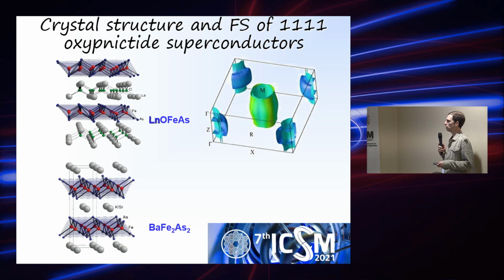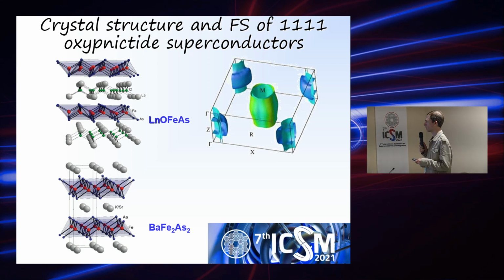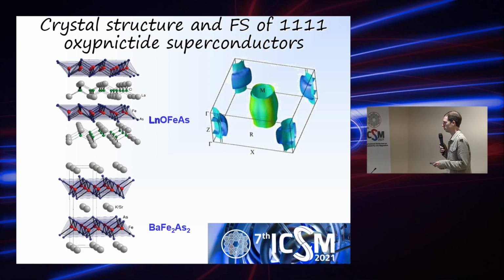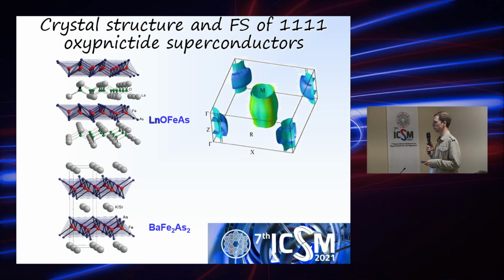So it's usual, and for the usual type of Fermi surface of 1111 compounds, one could predict some pockets and barrels in gamma points. Below the critical temperature of superconductivity, the large superconducting gap develops here, and also two crossed electron cylinders in M point.